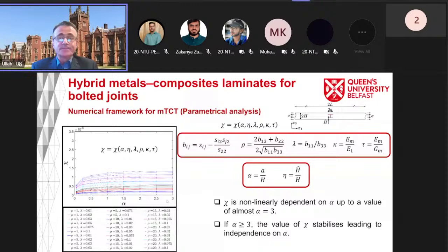And based on this, we can also find out how we will calculate this X. So in this case, for example, we can run different simulations for different values of lambda and this rho, which are material parameters. We can run different simulations, and we can create this surface here. And then from this surface, we can use some surface fitting, and we can calculate this X from given rho and lambda. And this P is basically this matrix here, which is just like polynomial coefficients.